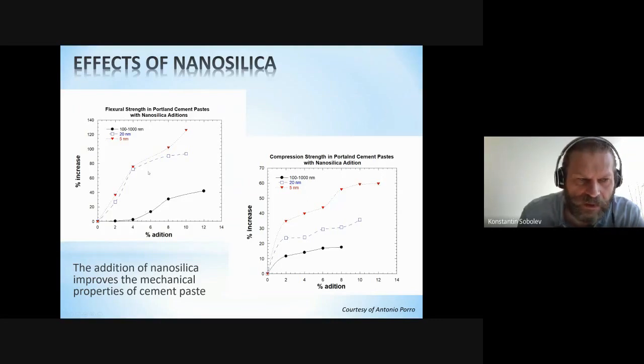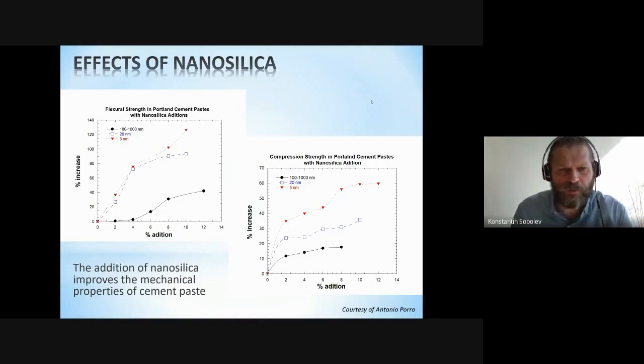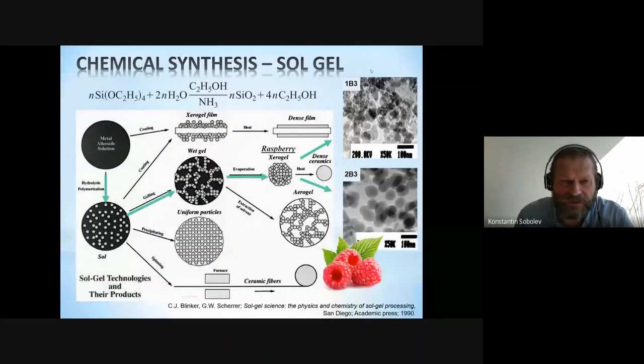And if we compare the effect of nanosilica on compressive strengths of Portland cement systems, we can see that the enhancement of flexural strength versus compressive strength was actually better. And obviously, my research group was discussing the use of nanosilica at extremely small dosages. Generally, we would use less than 1%, and often less than 0.5% dosage. The idea was that nanosilica and nanomaterials should provide considerable improvement at relatively small dosages. Otherwise, it may not be effective economically and practically for different reasons, which we're going to discuss now.